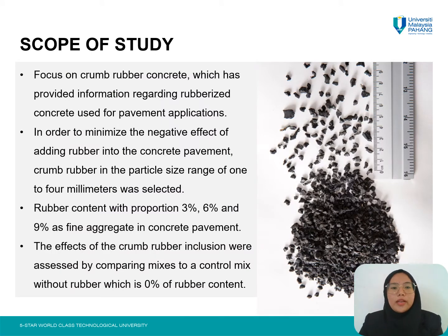The scope of study is focused on crumb rubber concrete, which has provided information regarding rubberized concrete used in pavement applications. In order to minimize the negative effect of adding rubber into the concrete pavement, crumb rubber in the particle size range of 1 to 4 mm was selected. Rubber content proportions are 3%, 6% and 9% as fine aggregate in concrete pavement. The effects of the crumb rubber inclusion were assessed by comparing the mixes to a control mix without rubber, which is 0% rubber content.